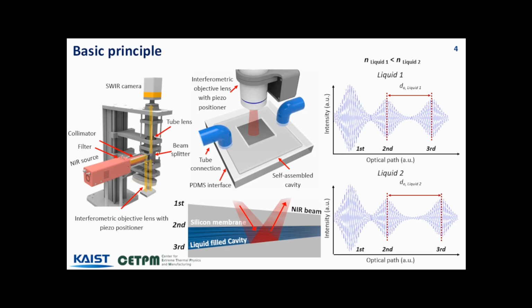So in this study, we present a platform that integrates a near-infrared interferometer with a self-assembled cavity in silicon for the measurement of liquid refractive index. The self-assembled cavity featuring multiple parallel fluidic ports is fabricated. This cavity is then bonded to a PDMS interface, which includes one optical access hole and two tube connection holes.